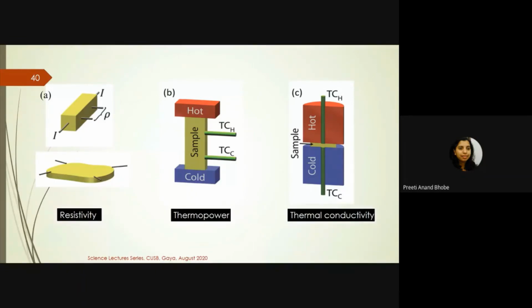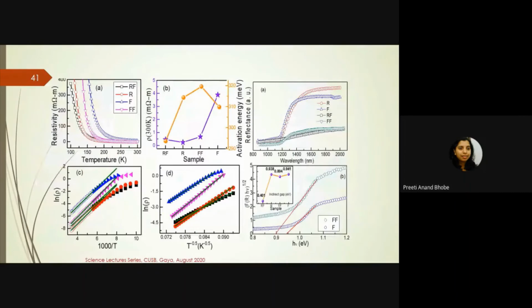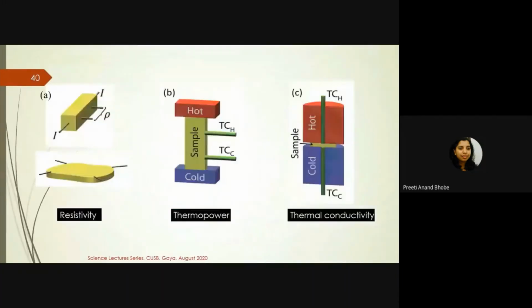So when we measured the resistivity of these materials, we did see a change. But if you measure thermal conductivity or Seebeck coefficient, it does not depend upon the morphology because of the nature in which these measurements are done. Also, the yield of a material prepared by hydrothermal synthesis is very little. So you have to make the material in batches and batches and batches to get a sizable amount to make a nice, good pellet for resistivity, thermopower or thermal conductivity measurements.